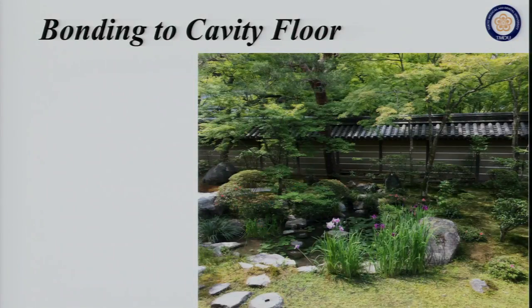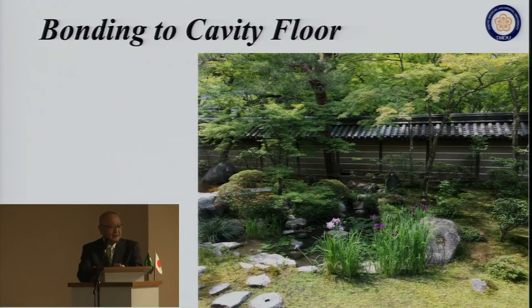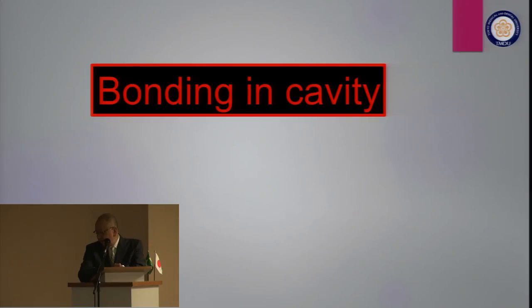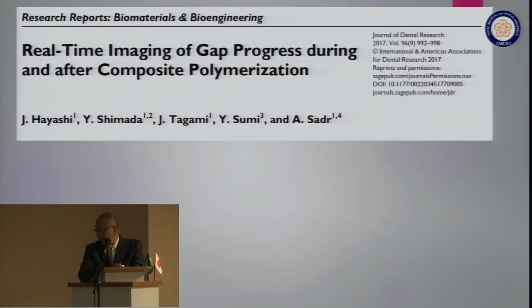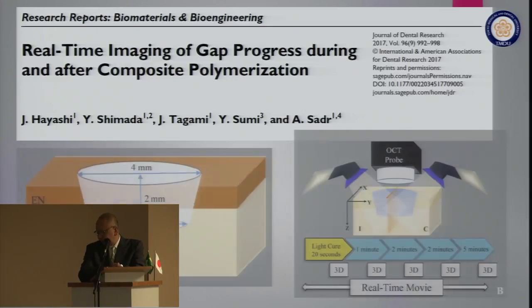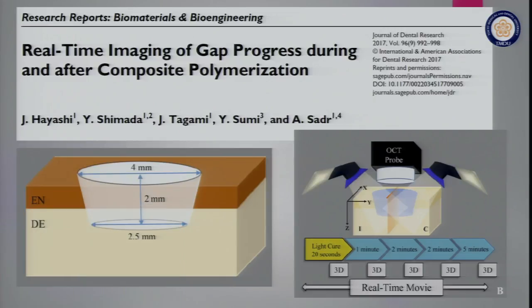Now, in the clinical situation, we have to think about the bonding to the cavity floor. The cavity floor is a very complicated situation in the clinic. Okay, we could observe the gap formation in the cavity as a real-time observation using a new technology named optical coherence tomography, OCT. We prepare the cavity here, consisting of enamel and dentin, and we fill the composite after the bonding procedure, and we apply the light curing. Then we observe the interface.